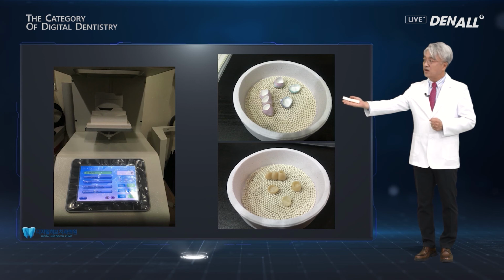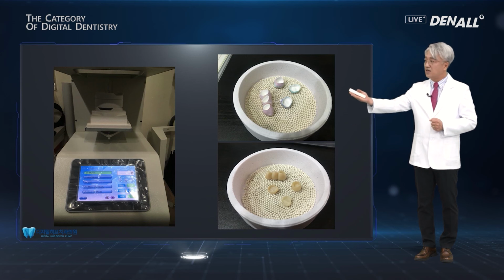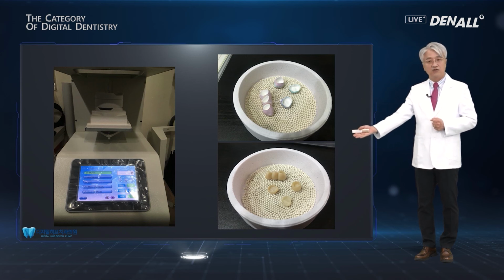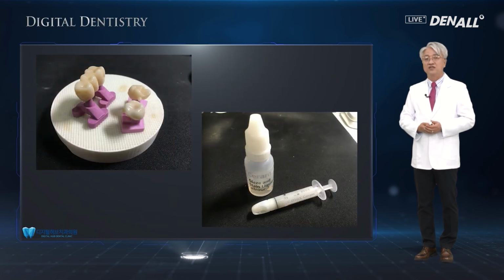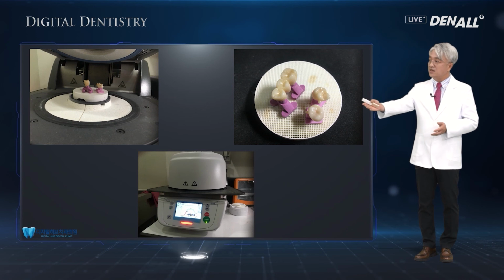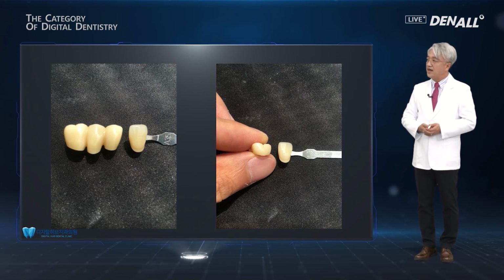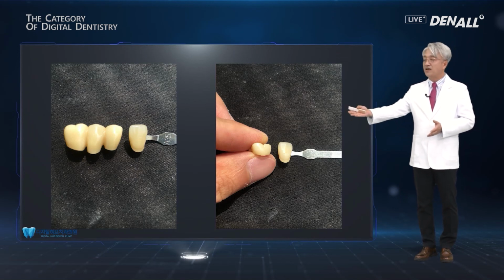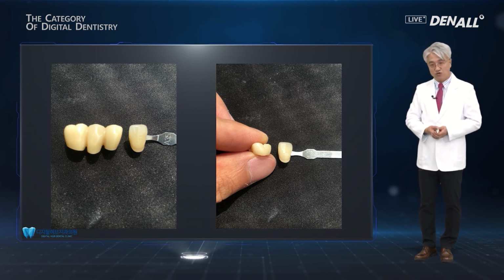The colored zirconia blocks need to be baked at about 1500 degrees of temperature. Then it's recrystallized, and then you have good size and very natural-colored teeth. And then stained, or if not stained, it's glazed. And then another step of glazing, sintering, and the final prosthesis is made. And shade 5, and you compare the shades, zirconia aesthetically, you can see it's very good.